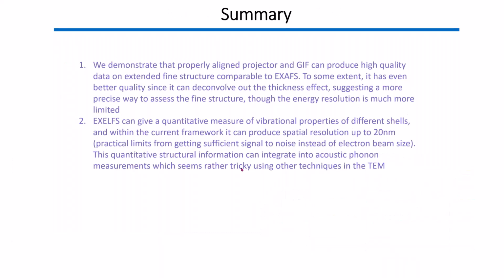So to summarize, we basically demonstrate that if you properly align the projector and the GIF and image filter, it can produce high quality data on the extended fine structure, which is comparable to EXAFS. And to some extent, you probably have slightly better quality in the sense that it can deconvolve the thickness effect. Although the energy resolution is much more limited, of course, in this case, and electron beam damage is also much more pronounced, which places harsher demands on sample preparation.